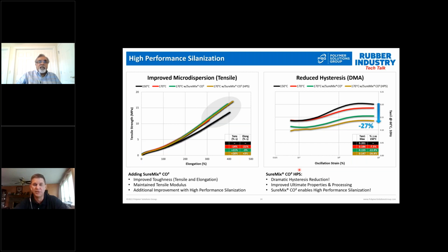But for the control, you see a big drop in the tensile and elongation. What's happened there is you've gotten pre-scorch, some pre-cross-linking in the mixer during processing. As a lot of you know, if you continue to mix while your compound's starting to cross-link and pre-scorch, you're going to tear the polymer, reduce the molecular weight, and lose ultimate properties. You see the two compounds with SureMix CO squared, the green and the yellow curves. We're able to protect the compound during the higher temperature and get a very good tensile and very good elongation development.